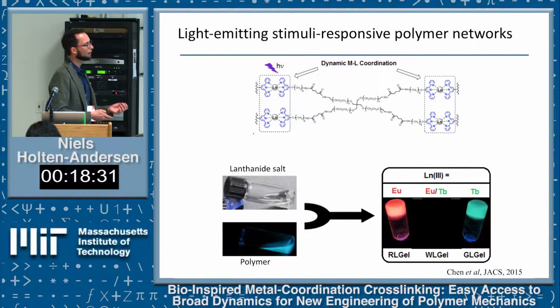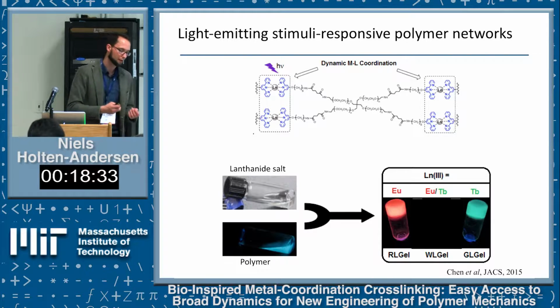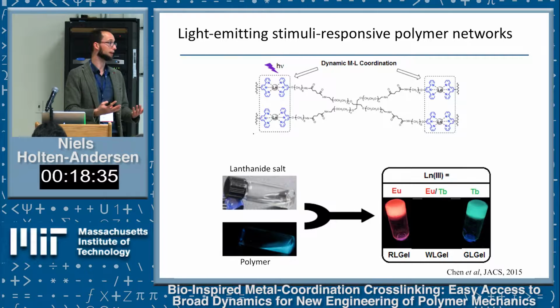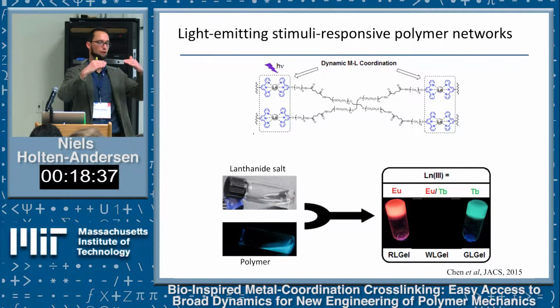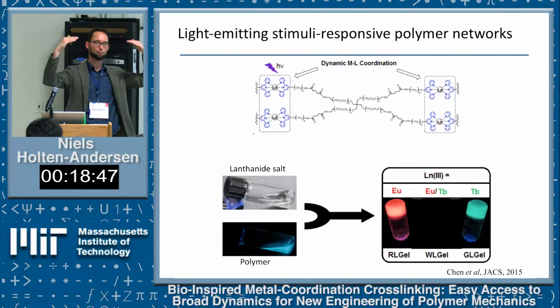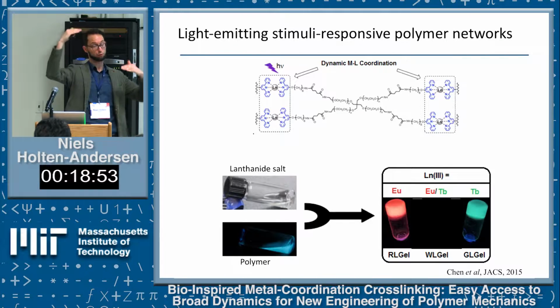What's cool about it is you now have a material that emits white light when excited with UV, and depending on what stimulus you throw at these materials, it'll change color. The reason for that is you have this balance of red emitting bonds and green-blue emitting bonds. If those bonds respond slightly differently to temperature, mechanical stress, or pH, these two ratios will shift and you get a color change.